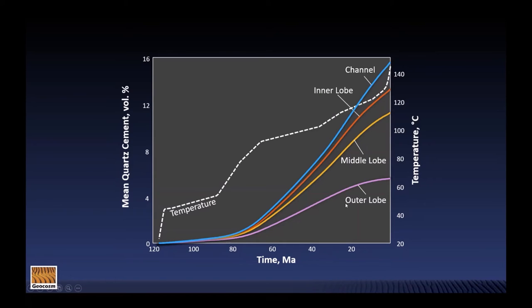On the other hand, if we think about the outer lobe here, we have a lot of microporous detrital clay in the system. Some of that detrital clay is actually sitting on the surface of the quartz grains, and that's reducing the surface area for nucleation. The additional effect that that microporous clay has is that it creates tiny little surface areas, independent surface areas, on the scale of microns. And so even though quartz might nucleate on these little pores between the detrital clay particles, the areas of those surfaces are really small, and so they quickly grow euhedral faces, and so the quartz growth rate invading into those micropores is extremely slow.